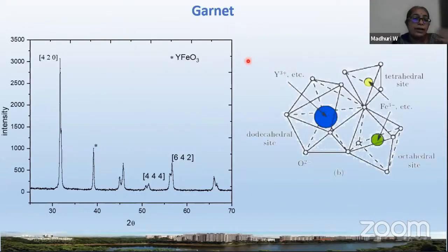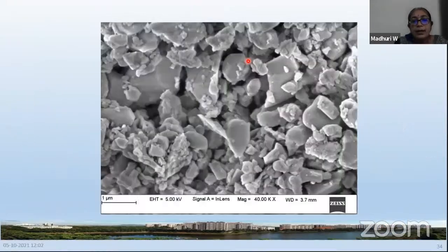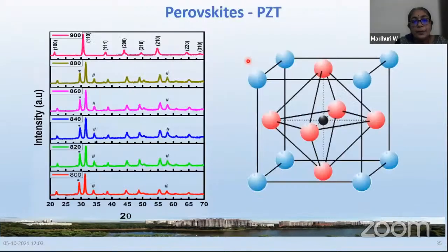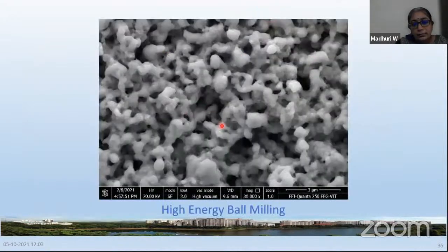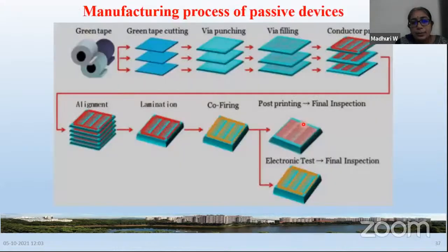And this is another kind of ferrite which is called garnets. And this is also by ball milling here. And these are perovskites, the ferroelectric materials. And this perovskite is PZT, that is lead zirconium titanate. And this is made by high energy ball milling along with microwave sintering. You can see there is a uniform grain structure. I'm sorry for the dull imaging, but you can see the uniformity in grain size. And as you do it with microwaves, that's the best part. Now, how to come to your device?